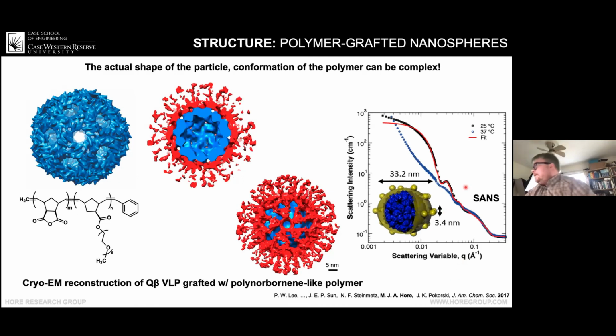I'm looking on my monitor here. It's hard to see. First of all, you can see the error bars for the measurement are, if you really look, there. They're smaller than the points. So that's one indication for a single measurement. If I was to take several independent measurements, we would get almost exactly the same scattering pattern. So the scattering patterns themselves are actually not scattered, if I want to use your words.